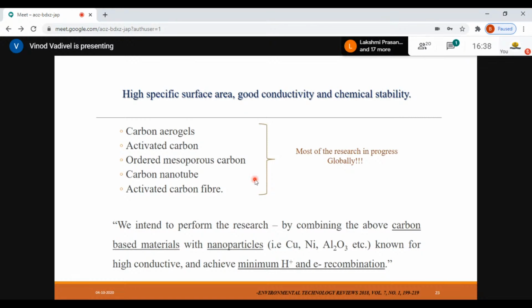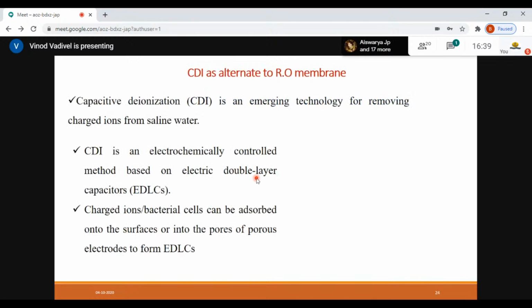And now the system is mainly focused on developing aerogels with carbon molecules, and also activated carbon, ordered mesoporous carbon, carbon nanotubes, and activated carbon fibers. So these are the mainly focused aerogel-based materials, mostly on the carbon phases. Our role is to combine the carbon-based materials with nanoparticles. It can be copper or nickel or aluminum oxides, known for high conductivity, and achieve a minimum recombination effect. When we talk about photocatalysis, you need a minimum recombination effect. The electron-hole pair recombination should be less, so that you can generate reactive oxygen species. So this is again the process that we are working on.